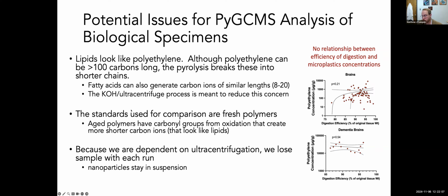There's also concerns that we think we're looking at very, very old plastics, but all our standards are using fresh polymers, and that potentially means we're underestimating concentrations. And also because we're depending on ultracentrifugation to isolate pellets, we're likely losing yield with each run that we do, so nanoparticles will not be pulled down into the pellet as efficiently as larger particles.